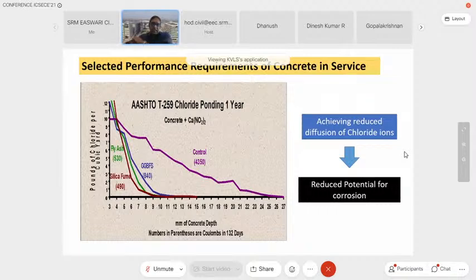But now the same concrete, when it was designed with GGBS or fly ash, the strength was kept the same. So we achieved the same strength with the use of GGBS and fly ash. But you notice what happens to the chloride profile here. The chloride profile is much sharper when we use GGBS or fly ash, which means chloride is not able to penetrate as easily into this concrete made with fly ash or GGBS as compared to control.